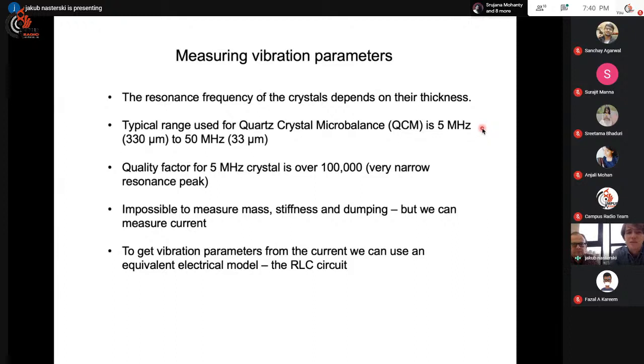So maybe you remember in physics class when you were measuring the natural frequencies of pendulums. All you have to do is count the cycles and divide it by the time, and you know the natural frequency. But how do you count 50 million cycles per second? Also, it's impossible to measure this mass, stiffness, and damping directly when we use quartz crystal for measurements. Instead of doing that, we can use a technique of applying an equivalent electrical circuit.